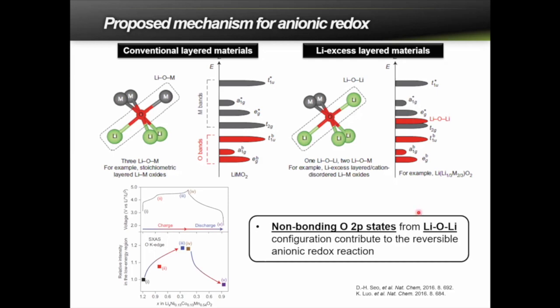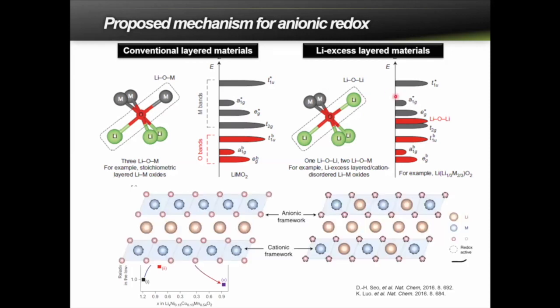So this kind of local oxygen environment is typically made in, of course, lithium excess material, which has some of the lithium occupancy in the transition metal layer. As you can see here, in the conventional layered structure, the transition metal sites are all occupied by transition metal, but here some of the lithiums are occupying them. So oxygen with lithium-oxygen-lithium bonding is going to be produced in this particular material group.